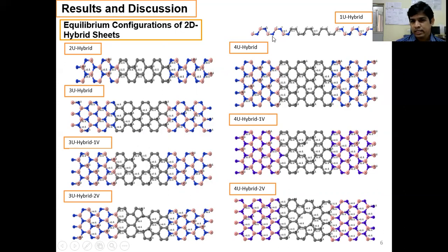First, it comprised around 16 boron nitride molecules. By replacing a single molecule by carbon pairs one by one, the band gap gradually reduces. First of all, this system was an insulator, and by gradually replacing the BN molecules, it gradually transformed into a conductor.